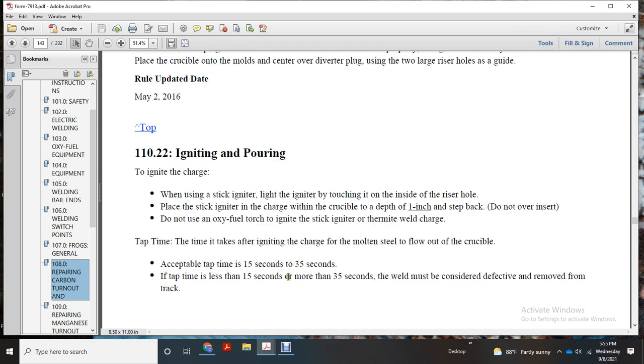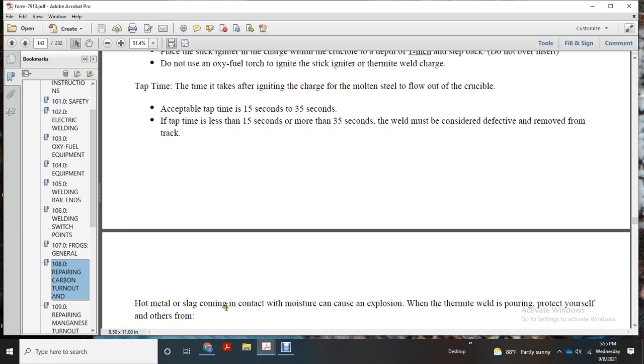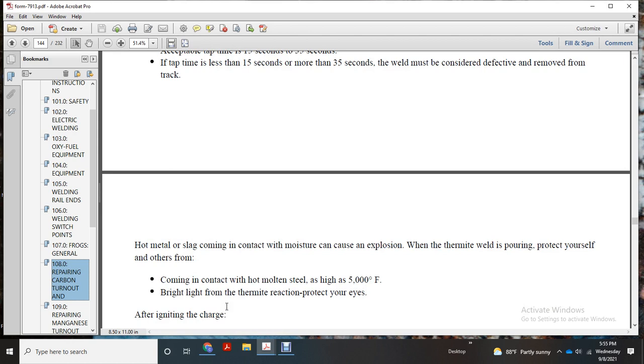If the tap time is less than 15 seconds or more than 35 seconds, the weld must be considered defective and removed from the track. Hot metal slag coming into contact with moisture can cause an explosion. When pouring the thermite weld, protect yourself and others from coming in contact with hot molten steel as high as 5,000 degrees. Bright light from the thermite reaction, protect your eyes.